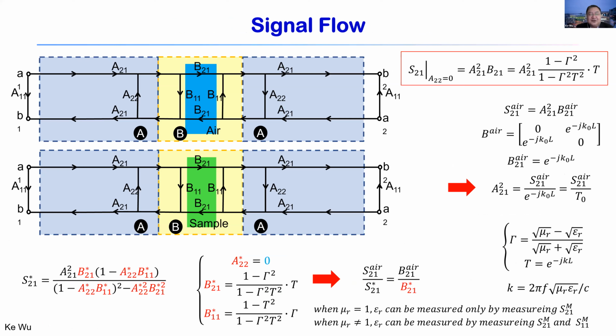Actually, we can use a signal flow chart to describe this, but I will not go through the detail of that. Just to let you know that you have two scenarios here. One scenario is that we assume the material under test is replaced by air. Usually, this should be done prior to the actual measurements of the material under test. So you do the measurements first with air, and this is like a calibration process. I would consider it a second calibration, because you have the system calibration, but this calibration is related to the specific measurement conditions here. So these two measurement procedures generate a number of equations. I will not go through this. You can see this.